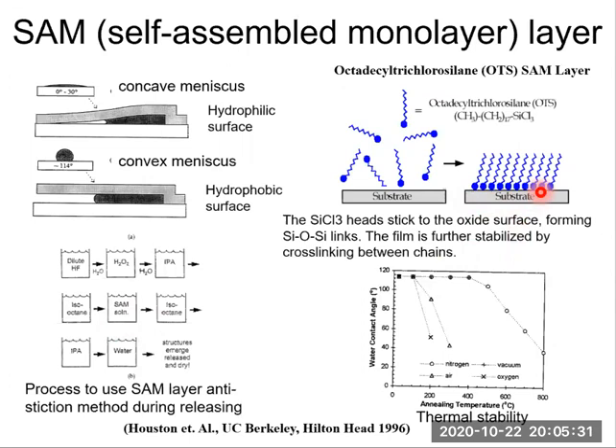So the surface is hydrophobic now. Then the process is reversed: iso-octane, IPA, water. And finally, the wafer or the chip is removed from the water. During the drying process, the meniscus is convex, so there's no contact and no stiction. This is anti-stiction using a SAM layer.